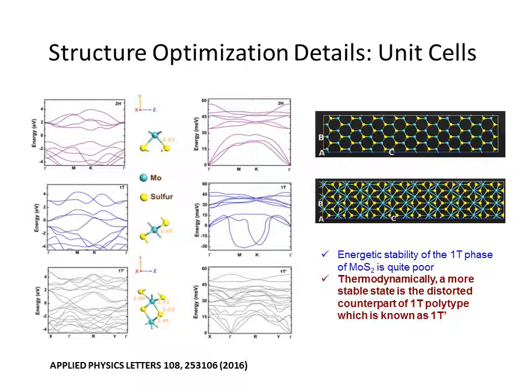Further, to study the dynamical stability of the 2H, 1T, and 1T' phases, we employ DFT calculations and obtain phonon dispersion curves. In order to obtain the phonon dispersion curves using frozen phonon calculations, we have formed the dynamical matrix of the system with a repetition of 9x9x1 in X, Y, and Z directions. Considering the phonon band structures obtained for metallic 1T MoS2, we clearly see the presence of imaginary or negative frequencies.